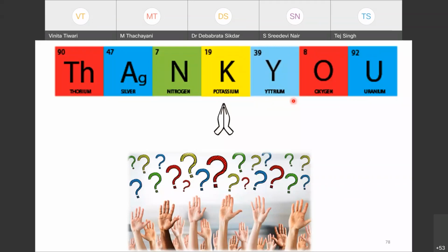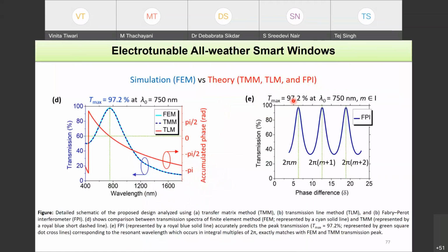Those results will be considered okay for publications? Yes. As long as you back your simulation result with theory, and you are able to show that your theory and simulation are matching, then they are considered good results. Nobody will stop you in that case. As you can see in our case, we have mastered this transmission line theory in such a way that they give you a perfect overlap. This is the work I have done during my postdoc at Imperial College London. After that, I started in 2015, I believe. Over these 5-6 years, we have improved the theory slowly, so that you see this kind of amazing match.